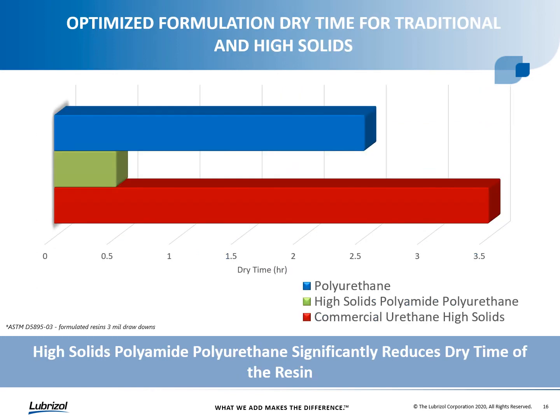I mentioned earlier in the presentation that one of the features of this high solids polyamide polyurethane was that it was fast drying. And in this chart here, we see when comparing against the traditional lower solids polyurethane in blue, and then the commercial high solids urethane product in red, that the high solids PUD really does have fast drying properties at less than a half hour being dry, whereas the traditional system is upwards of 2.5 hours, and the commercial high solids urethane is closer to 3.5 hours.